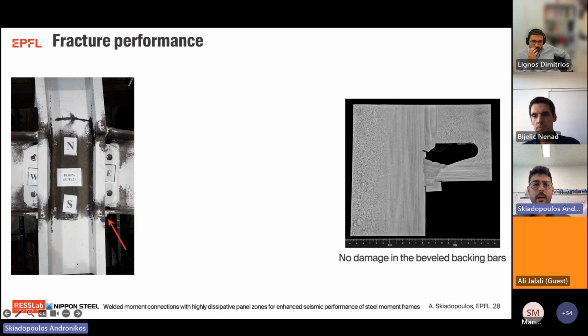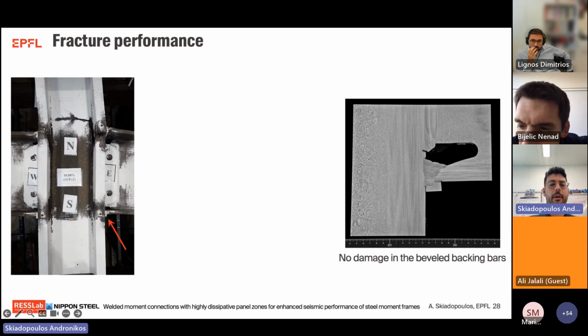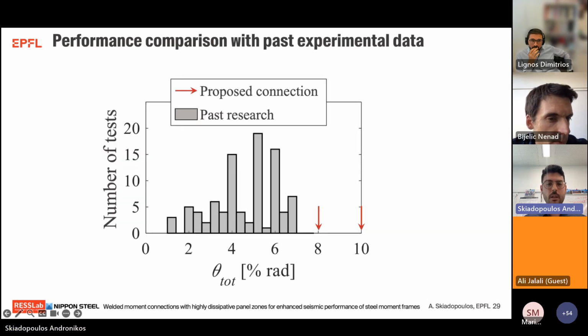The performance of the bevel backing bars that we proposed previously is also highlighted in this slide due to macro etching that was extracted again from the beam web centerline. And this indicates that there was no crack initiated from the weld root of the bevel backing bar, even at lateral drift demands exceeding 9% radian. And this gives credit to the proposed bevel backing bar design that practically minimizes the fracture potential in that region.